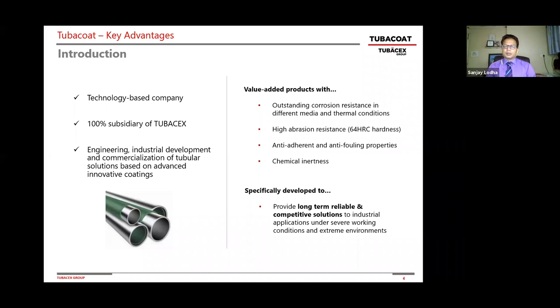With this multiple complex procedure, we get the TubaCoat technology, and it brings out properties that combine a silica ceramic-based material along with multiple inorganic metal oxides such as zirconium, zinc, sodium, magnesium, and other compounds, fused into an enamel to give you outstanding corrosion resistance in different media and thermal conditions, temperatures up to 1500 degrees Fahrenheit, hydrochloric acid, sodium hydroxide, sulfuric acid, and many corrosive conditions.